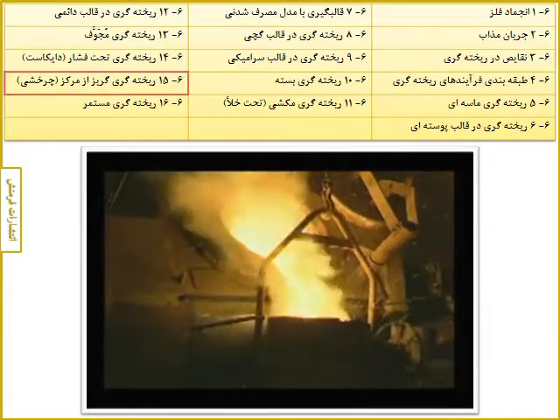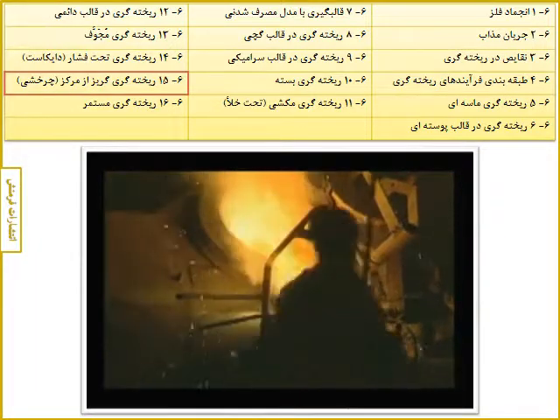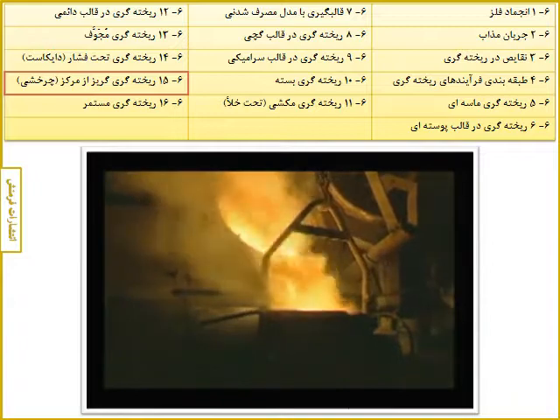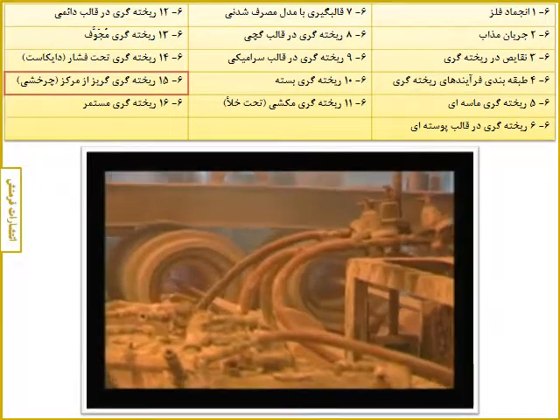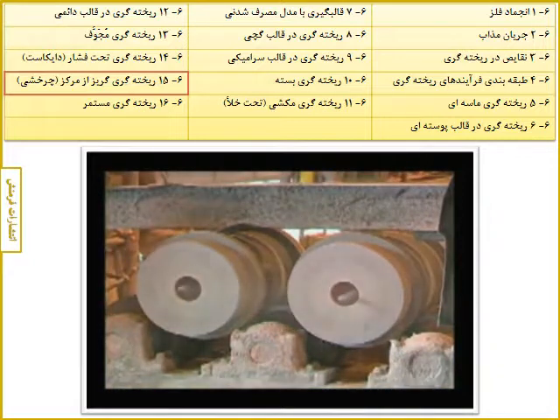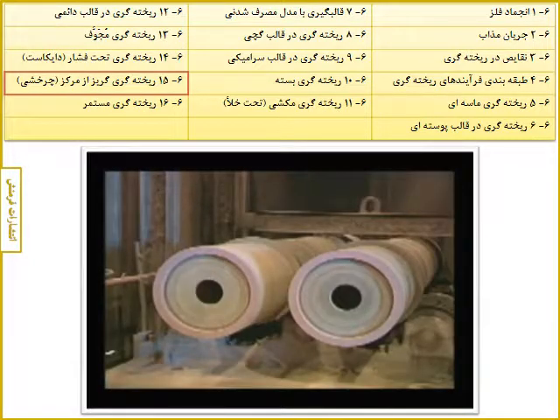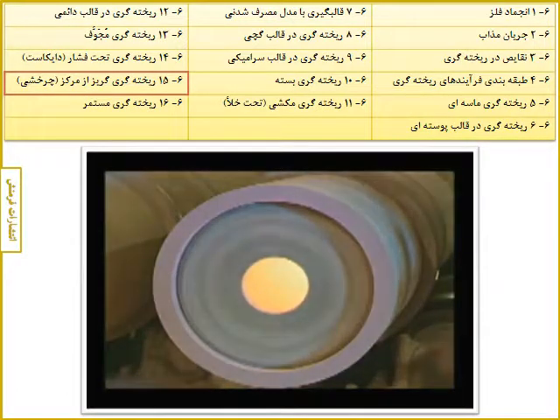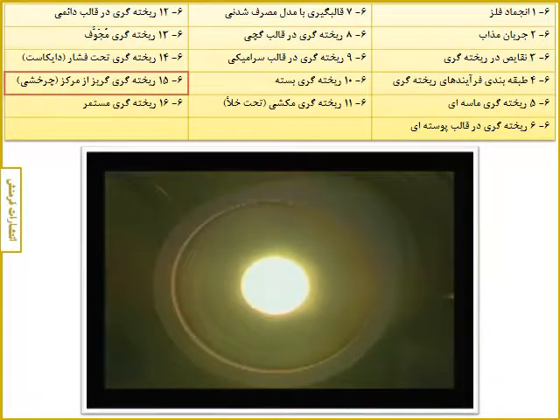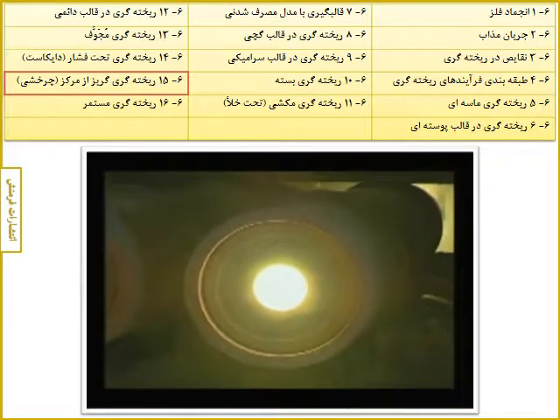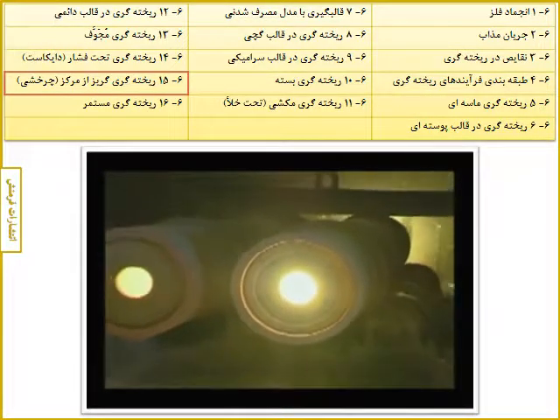The spinning casting fills any shrinkage voids under high pressure from centrifugal force. Slag, dirt, and dross, being of lower density than the metal, spin to the bore or center. The result is a very clean, very dense, very uniform casting. Once the casting is complete, the tube is machined to remove the impurities that spun to the center during the casting process. Spuncast uses its vast metallurgical expertise to partner with its customers to improve products and processes.